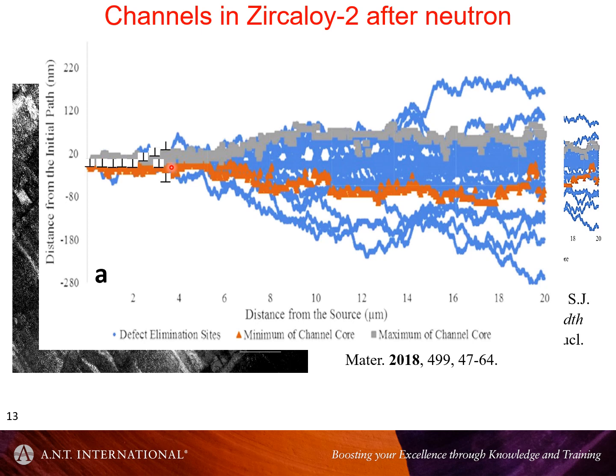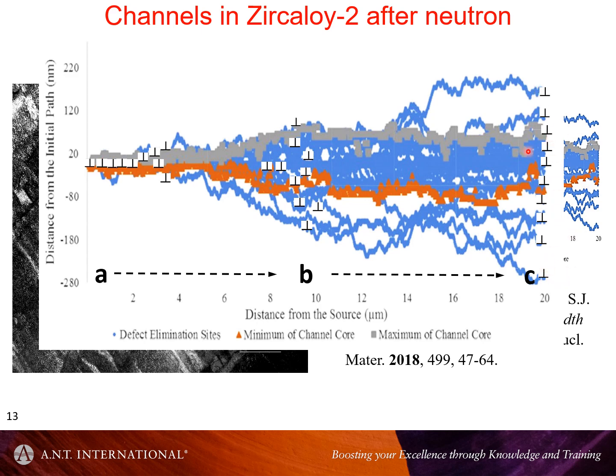And if you had different signs of, well, you wouldn't have different signs of dislocations. You'd have the same sign if they're moving in the same direction. And then at some intermediate spot, this volume of material which is being swept out, or which is interfering with the dislocations, increases as the dislocations climb further and further. And then at the end here, you have a region where you have this very broad distribution of dislocations. Now, once you got to this point, you've essentially got a subgrain boundary.